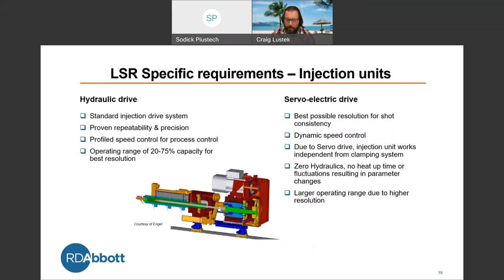You always have to look though at your operating range, that 20 to 75% capacity for best resolution. With LSR, under that 20%, we really want to make sure that we're getting a good material flow through our static mixer into our screw. Over that 75% limit, we're still metering in a longer cycle due to the fact that we have to get past that 75% range. So then maybe in turn we go to the servo electric drive, looking at the best repeatable resolution, dynamic speed control.